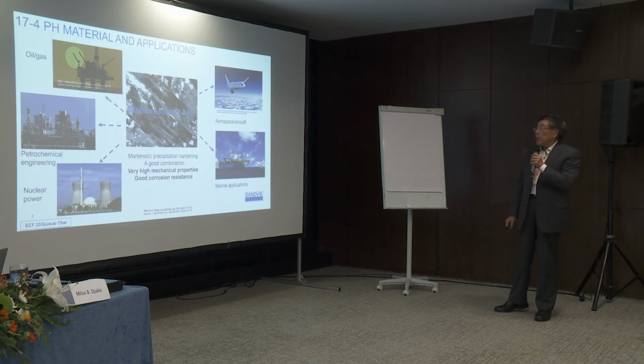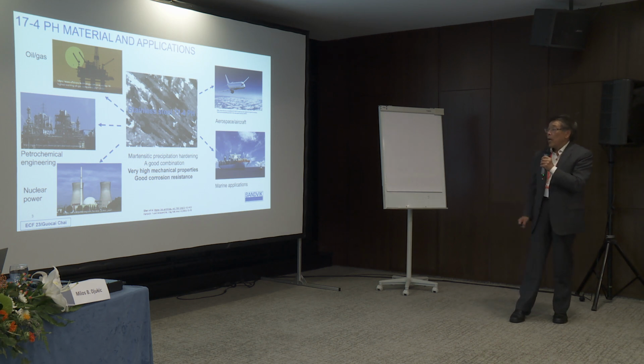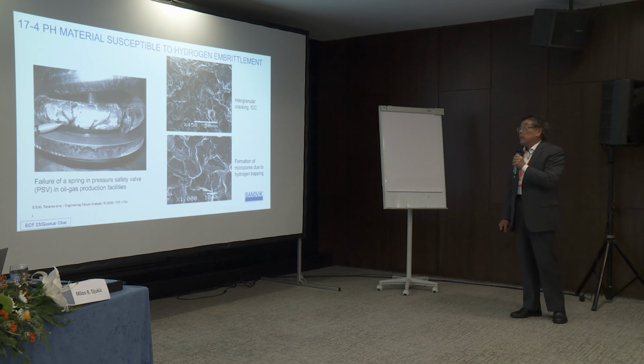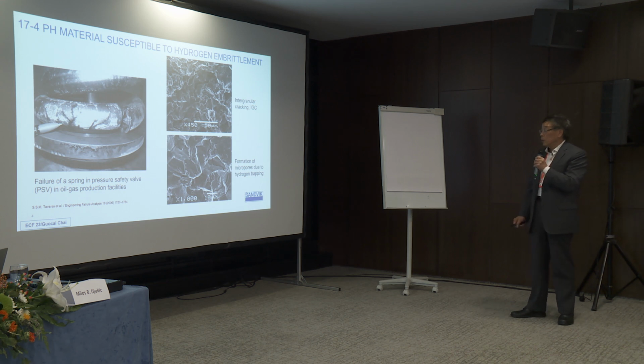17-4 PH actually is a well-known material. It is a precipitation-hardened martensitic steel with high strength and high ductility. So it has high performance and is widely used in different industries. But it was found this material is susceptible to hydrogen embrittlement. Here I show one example in a pressure safety valve in the oil and gas industry. You can see a crack here, and it's a very typical intergranular crack, with typical hydrogen voids.